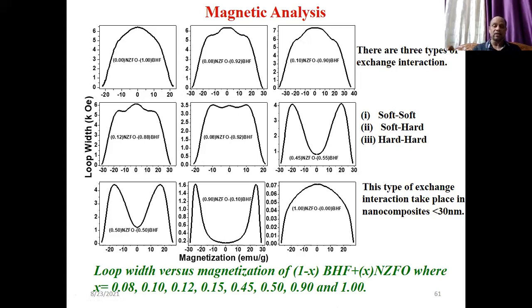But you will get this effect only when you see that this is also ball milled. One can say that it is due to the amorphous phase, and initially people were observing similar properties when you have an amorphous magnetic material. So it may be happening due to the amorphous phase, no doubt. It can be due to the amorphous, but in amorphous material they exist in a different way. Their magnetic properties from one amorphous grain to the other are different, because it highly depends upon the size of the material. That's why in the amorphous you will also get the same. But in this case, in a particular nano size, they interact with each other and show you different properties. So if you understand what exactly is happening, why is it important?